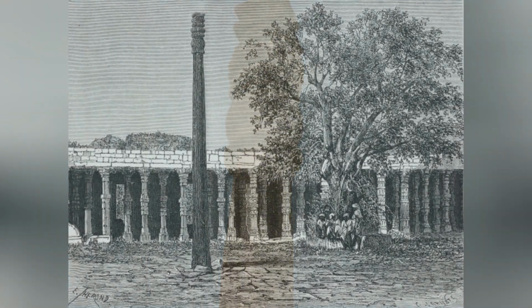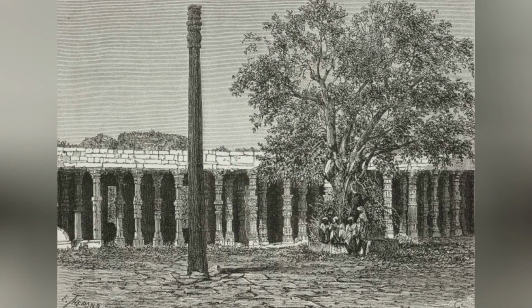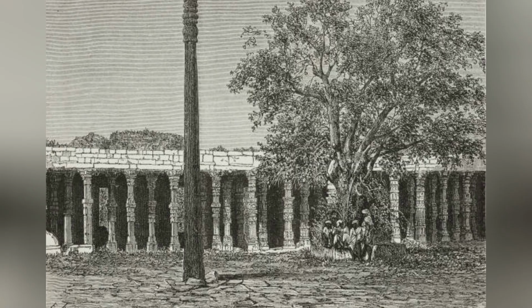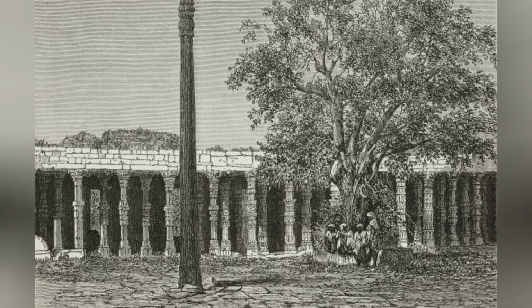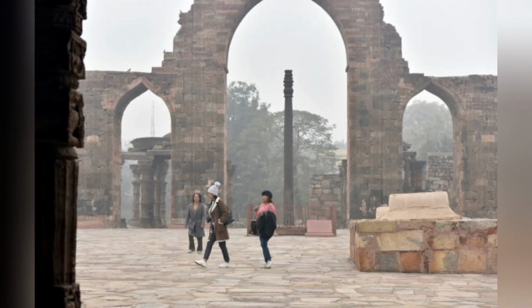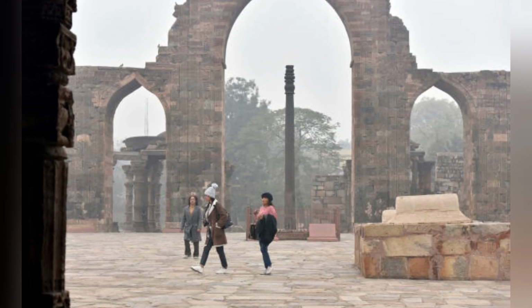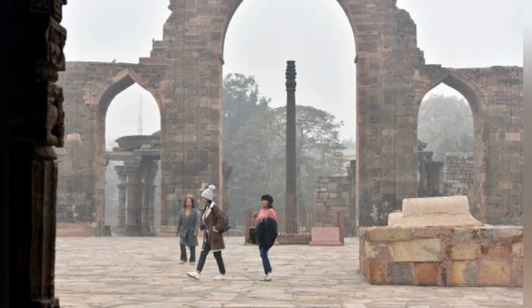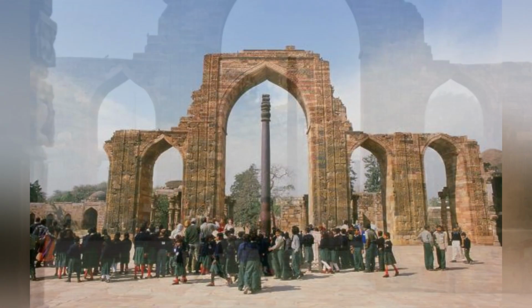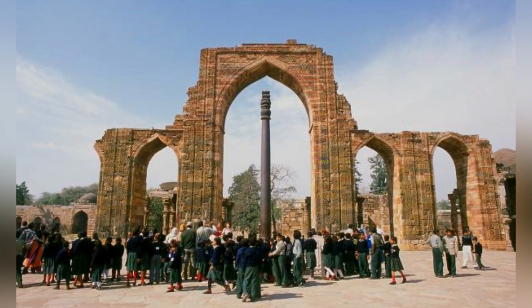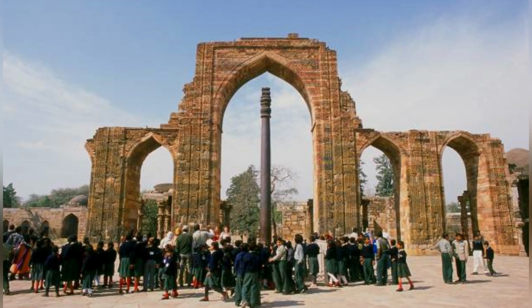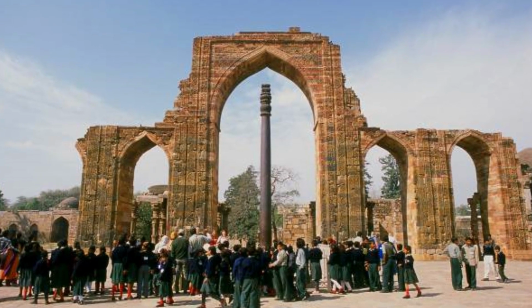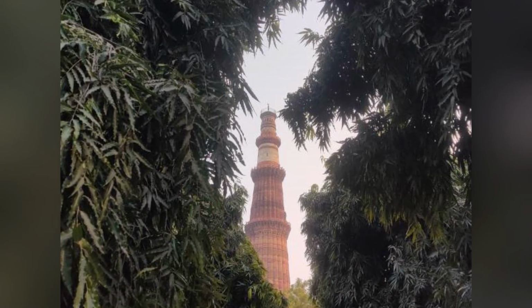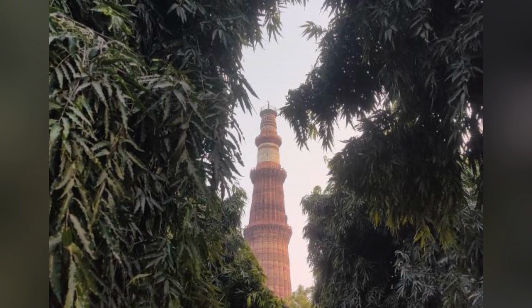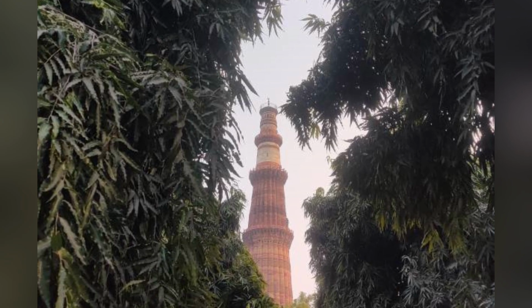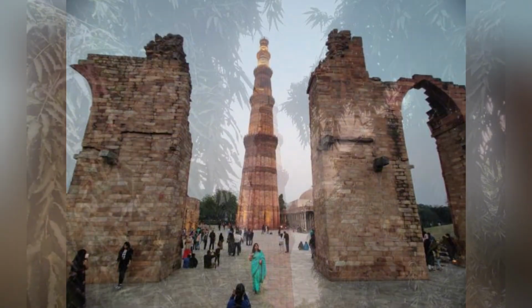The measurement of the pillar's dimensions, which has been conducted with increasing precision over the past century and a half, has provided evidence that the pillar has lost virtually no material to corrosion over its lifetime. The comparison of the current dimensions of the pillar with the estimated original dimensions, based on the construction techniques and the proportions that are typical of Gupta period iron objects, indicates that the pillar has lost less than 1 millimeter of its surface over 1600 years, a rate of material loss that is negligible by any standard, and that is consistent with the extremely low corrosion rate that has been measured by Balasubramanian's electrochemical testing.